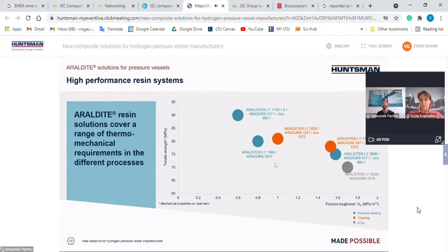So here we can identify each dot is actually a resin system that we reviewed before, and all the color chart correspond to the different manufacturing processes I was just talking about before. And here we can identify two different groups of products. The first one is high tensile strength and a regular, let's say, standard fracture toughness. This is because some of the customers, they don't care about the high fracture toughness because they manage the impact resistance, or they manage differently the aging or the endurance test based on their design. And they favor, in this case, some cost-effective resin systems that correspond to this first group and category.